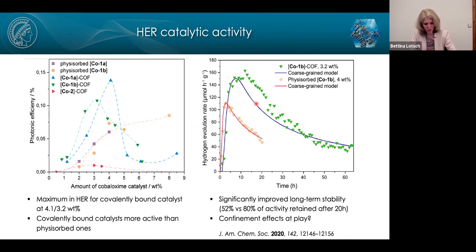This trend also is maintained in long-term stability. So as expected, basically, the covalently coupled system is more stable, more durable than the physisorbed system, which deactivates much earlier. We believe, or we think, that this could actually be, at least in part, due to confinement effects. In cobaloxime hydrogen evolution catalysis, in the intermediate stage, the axial ligand of the cobaloxime needs to come off, and then needs to coordinate back on the cobalt during catalysis. And if the axial ligand is lost, the catalyst is deactivated. And so we believe that perhaps in the pore of the COF, this coming off and going back on might be facilitated. So this is a possible interpretation of this better long-term stability.